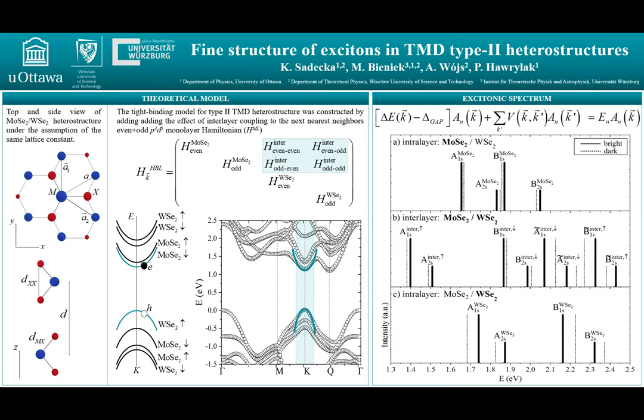So we start with determining the electronic structure of molybdenum diselenide tungsten diselenide from first principles. We obtain the type 2 band alignment and conduction band minima in Q point, as you can see here. Next, we perform the analysis of Kohn-Sham wave functions, allowing us to detect the leading layer and spin contributions, and construct a minimal tight binding model of this heterostructure, which allows us to understand the orbital contributions to Bloch states and study the effect of wave functions on the excitonic spectrum, so all the topological properties of the system.